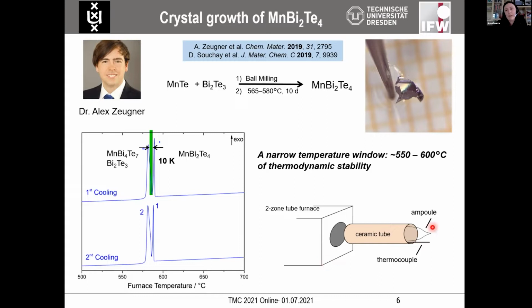So first of all, when you start synthesizing this compound, you have to deal with the starting materials that have very different melting temperatures. So basically you have solid manganese telluride and you have melt of bismuth telluride that melts almost 500 degrees lower. And then when you grow crystal from this melt, it is a heterogeneous solution. Then, as one can see from this differential scanning calorimetry data, when you start to crystallize the melt, so we are going down in temperature here, you first hit the crystallization peak of the ternary compound. So this 1 to 4 phase that you want to have. But then very soon after, only 10 degrees below, you have crystallization of other solids, one of them being bismuth telluride itself, and another one being another heterostructure in this family that I will talk about a bit later.